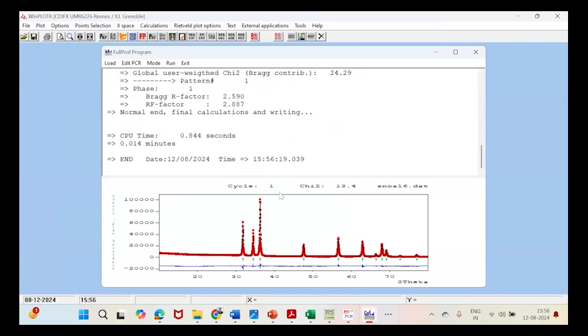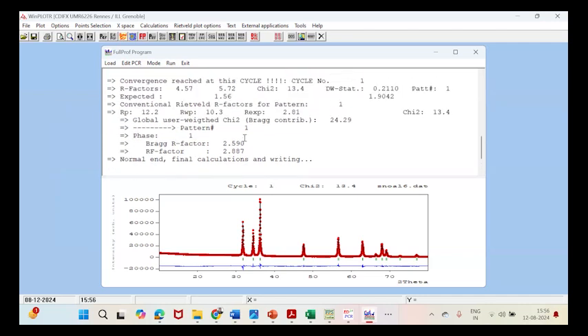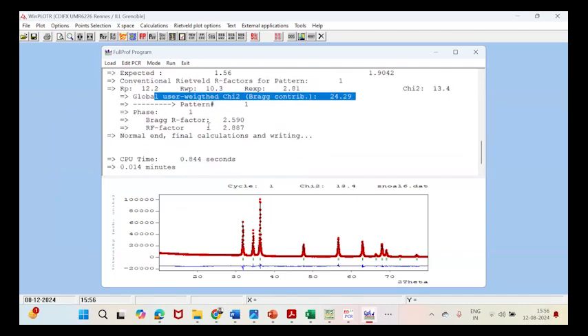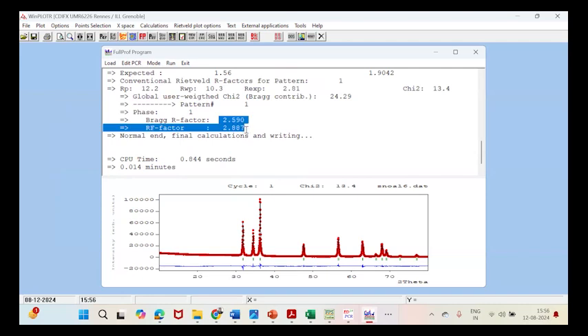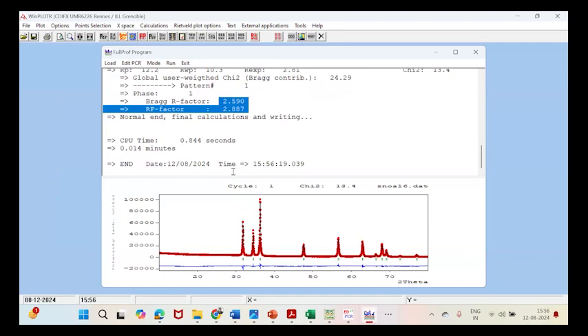If it is, I had given 10 cycles, but you can see after 1 cycle there's no change in the input, so it will stop. That will tell you that you have already refined your limit for that number of parameters, and these are the chi-square value, Bragg factor. This minimum number will give you the goodness of fit, how much better fitting you are having, and what scope is still there.